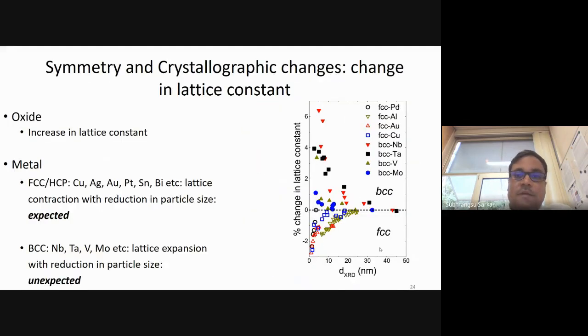Now, when you reduce the particle size, there are dangling bonds on the surface, and the systems are more energetic than the others. This also gives rise to a bit of strain on the system, especially in oxide nanoparticles. When we reduce the particle size, typically we observe that the particles shrink. And what do we mean by particle shrinking? The basic unit cell, the constructive element of the particle, reduces in dimension. Sorry, not in oxides, but in metals. In oxides, we see the exact opposite trend. The lattice constant increases and the particle expands a bit.